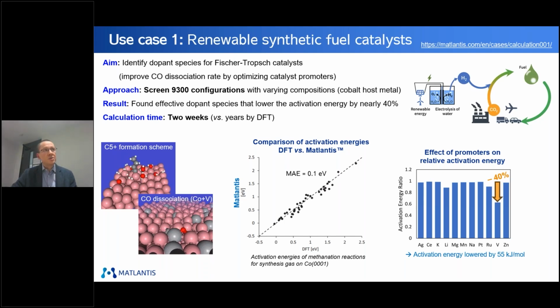Now you can also plot, as you see on the screen, the activation energy calculated by Matlantis and compare that with DFT, and you see the mean average error is actually very small. It's 0.1 eV. What we found is that vanadium gave a decrease of 40% of this activation energy. This was also checked experimentally. You see here a very good correlation both with DFT and with the experiments.